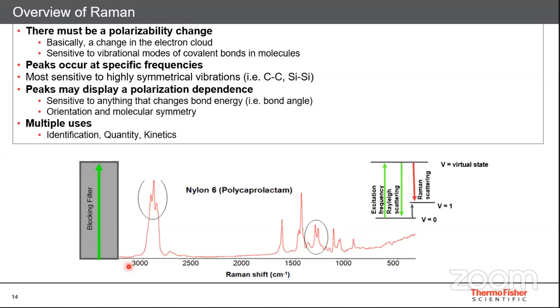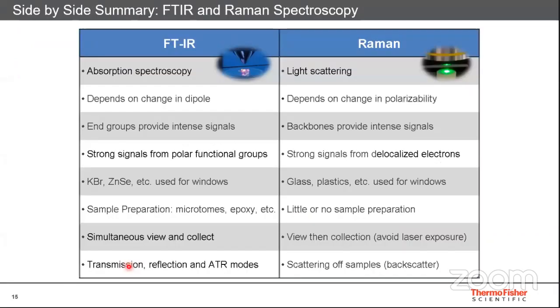Peaks occur, similar to IR, at specific frequencies. They are more sensitive to highly symmetrical vibrations. For example, if you have a polymeric chain with CH kind of bonds, you will see a very intense band in Raman spectroscopy. It is polarization dependent, and you can use it for identification, quantification, and also kinetic studies, as I said when talking about the lithium battery application.